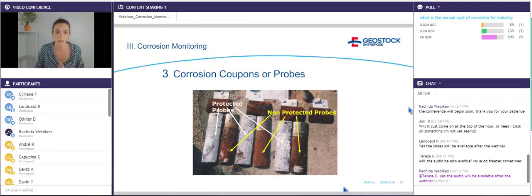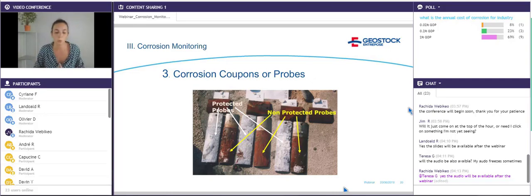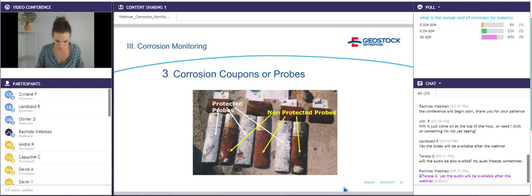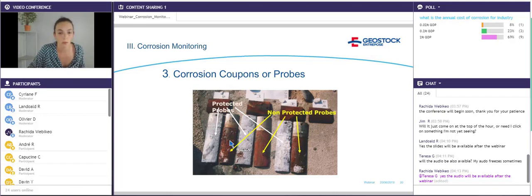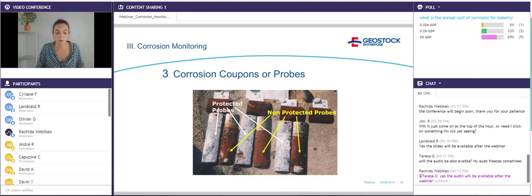The third method to check the effectiveness of the protection system is to use corrosion coupons. A corrosion coupon is a piece of metal with the same metallic composition as the casing. By monitoring its weight over time, we can deduce the corrosion speed. Here we have examples of corrosion probes: some connected to cathodic protection show white protective layers on the surface, while those not connected show rust on their surface — clearly demonstrating the difference. Some companies have also developed electro-resistive probes that can directly indicate corrosion speed without any handling.